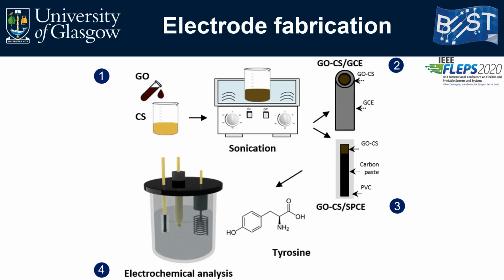The homogeneous graphene oxide Chitosan film was first prepared by dissolving a low molecular weight Chitosan powder in an aqueous acetic acid solution. This mixture was then stirred until a homogeneous solution was obtained. Graphene oxide was then added to the dissolved Chitosan solution before sonicating for 5 hours to obtain a homogeneous solution. This homogeneous solution was then uniformly dispersed on the electrode surfaces by drop casting.